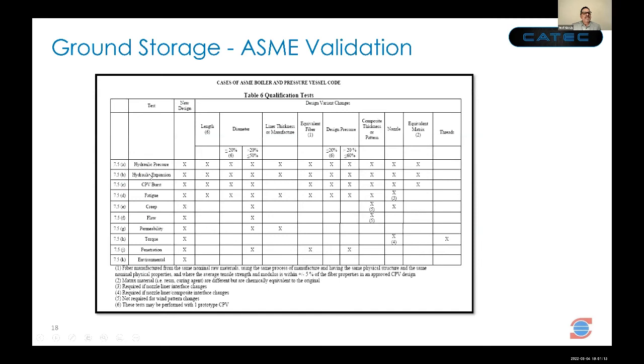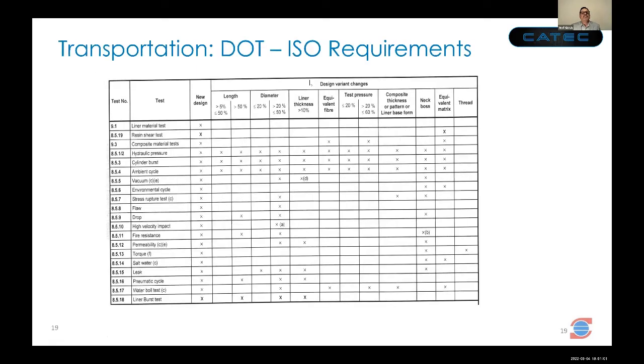We have to go through many tests in order to qualify these tanks, including burst tests, fatigue cycles, typically about 15,000 cycles. Creep means you keep it at a very high temperature for almost 3 months and they still need to have good burst strength. Flaw tests, you introduce several cuts on the tank and you still need to go through the fatigue cycles, permeation, penetration. Essentially, you actually have to shoot it with a bullet. And typical bullets will not penetrate these composites, so we have to use an armor-piercing bullet. And it still cannot burst. That's a requirement. And there are similar requirements from ISO standards.